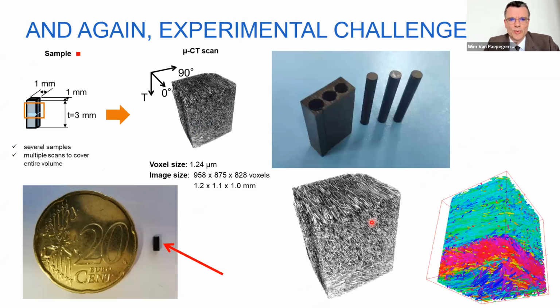And then to conclude my story, you see always my logic with the simulations and then the experimental challenges. Just a few last ones to close the story. Experimental challenges, and I also want to show you one very down to earth. You want to have this sample here, 1 millimeter, 3 millimeter high, to look at these fiber orientations. And I showed you here the fibers are more or less 90 in the middle, and here they are more or less aligned. And we would like to segment the individual fibers. That means that in a micro CT scan, you really need a very low voxel size. But that means that you also need a very small sample.